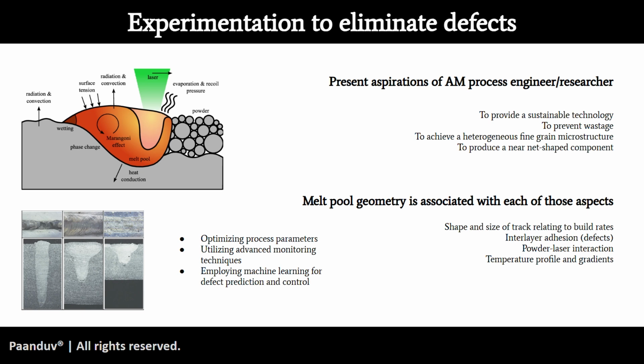While these are very noble aspirations to have, a significant amount of experimentation goes into attaining these goals. And at the core of it, much of the experimentation goes around understanding the melt pool geometry, understanding the microstructures, using fancy experimental machines at times. For example, the shape and size of a track relating to build rates, interlayer adhesion, powder layer interaction, powder laser interaction, temperature profile and gradients, and there are many other physics that is indicated.